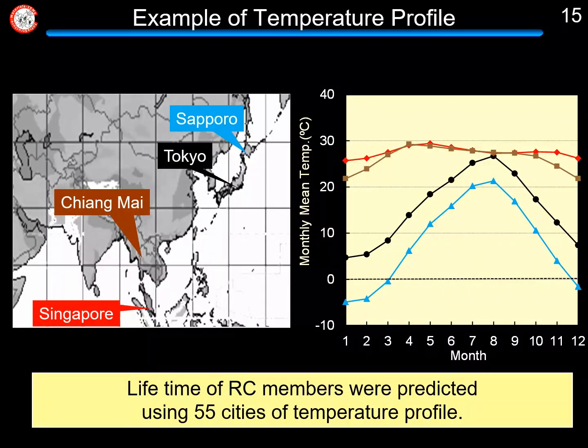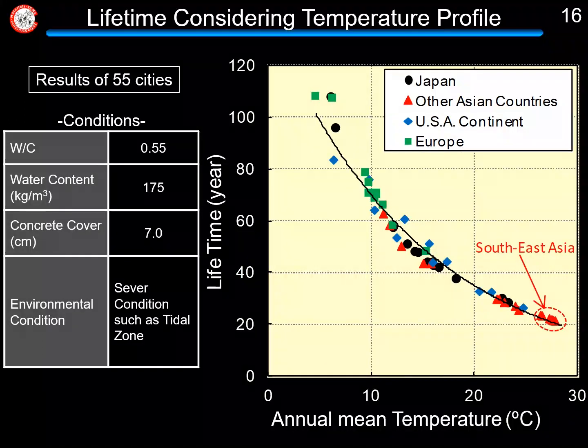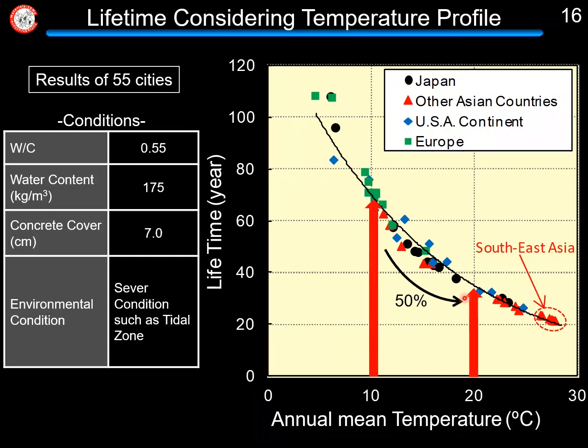An example of a temperature profile is shown in this slide. In this calculation, the monthly mean temperatures used at 55 cities for lifetime prediction are shown in this table. This graph shows the lifetime of reinforced concrete in each city, and the x-axis shows the annual mean temperature of each city. From this, it is predicted that the lifetime becomes almost half with a 10 degrees centigrade annual mean temperature elevation. And the lifetime of Southeast Asian countries becomes 70% of that of the region where the average temperature is 20 degrees.